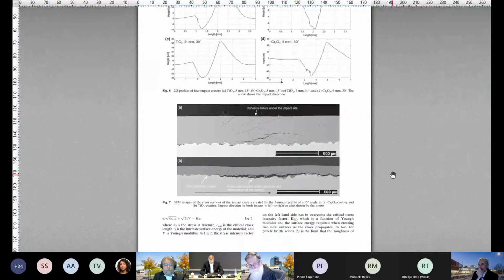Yes. So indeed, the coating is about 3 times thicker. The chromium oxide compared to the TiO2. So wouldn't it be very difficult to compare these two materials when you have such difference in the thickness of the coating?